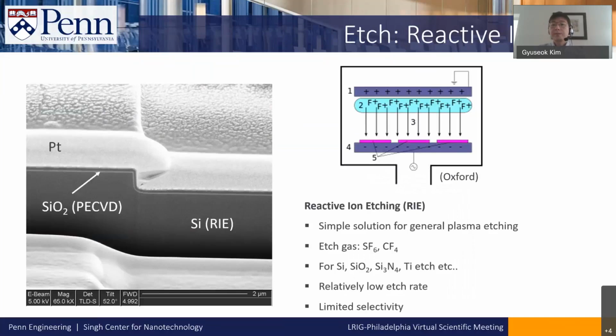So let me introduce two etch tools, some representative etch tools. One is reactive ion etch. This is one of the most popular etch tools. In this tool, we use SF6 or CF4 gases. So we use fluorine ions to etch silicon, silicon dioxide, silicon nitride, or titanium. It's very popular, easy to use, but it gives a relatively low etch rate and limited selectivity of the material to the photoresist.